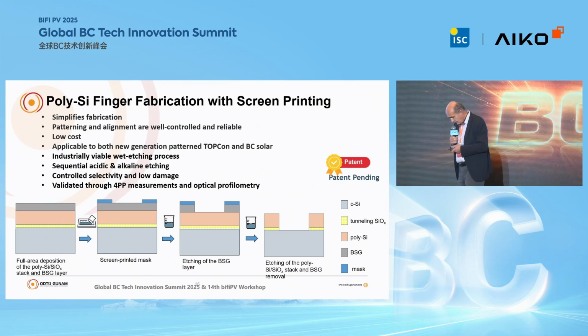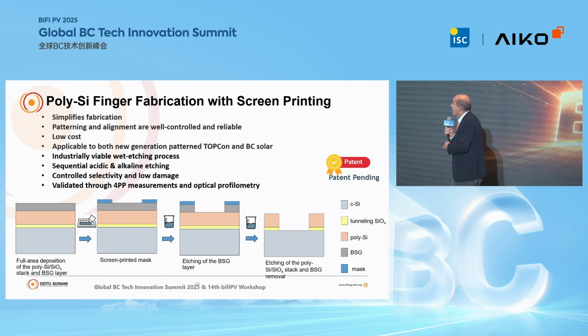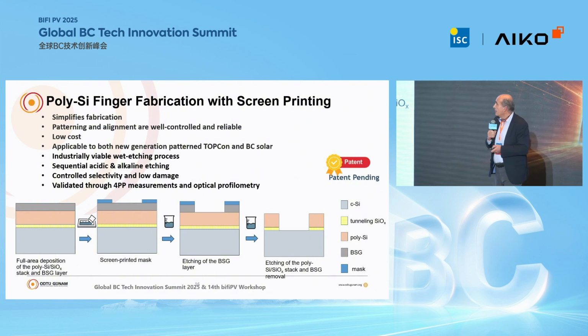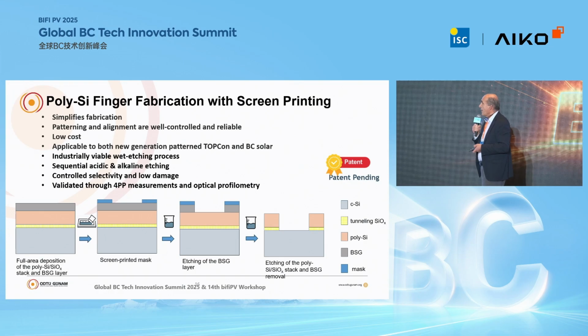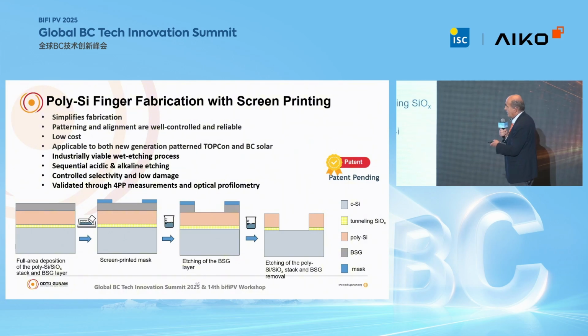Well, the second technique is based on screen printing. Screen printing is a simple process, and it simplifies the fabrication. Well, the patterning and alignment are very controlled and reliable, and it's a low-cost technique applicable to both new generation TOPCon and also IBC solar cells or BC solar cells. Industrially viable. In this technique, you just put a mask layer by screen printing and just etch the poly layer down to the surface of silicon.